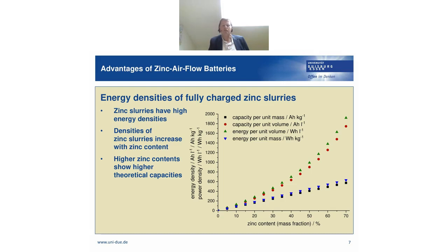So these zinc slurries have a high energy density, and this is depicted here on a per unit mass basis and on a per unit volume basis. On the x-axis, you'd see the zinc content. So this is just the weight percent of zinc. And when you look here, 70% zinc slurry has around 600 watt-hours per kilogram and almost 2,000 watt-hours per liter. So the point is how to make use of this high energy content in a zinc air battery.